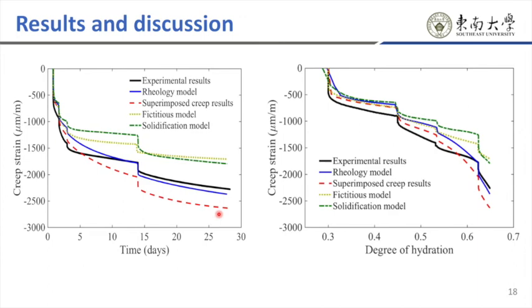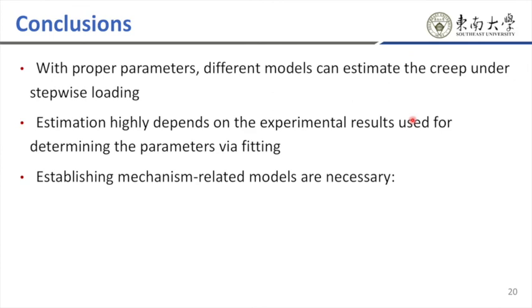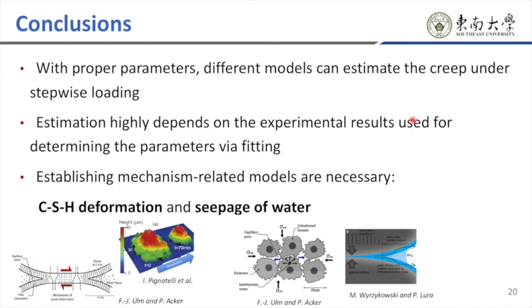In conclusion, with this simple assessment of different models, we can see all models underestimate creep at early age. To be honest, all the models are extensively dependent on the fitting results of experimental data, especially when the fitting results cover a long-term duration. More systematic experimental results are necessary for a better assessment of different creep models. However, one thing is clear: establishing mechanism-related models is of high necessity, which considers CSH shape deformation and seepage of water.